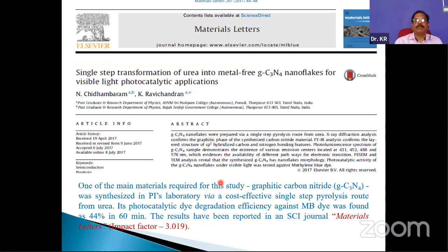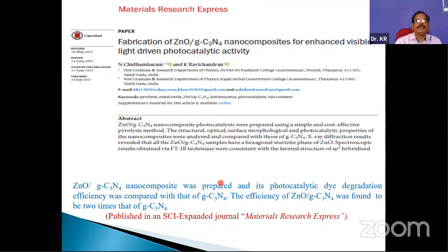In the first part of the work, we prepared graphitic carbon nitride, a semiconductor material, also a photocatalyst, having a band gap of nearly 2.2 electron volts, and found that the photocatalytic efficiency of the material is only 44%. Then we added zinc oxide along with the graphitic carbon nitride and prepared nanocomposite films on